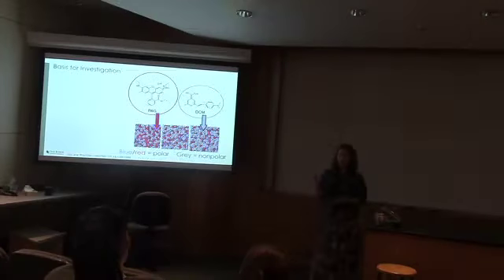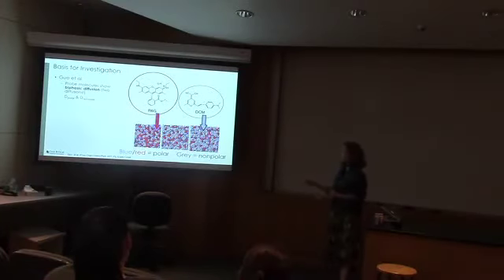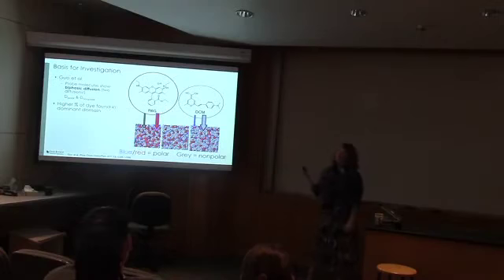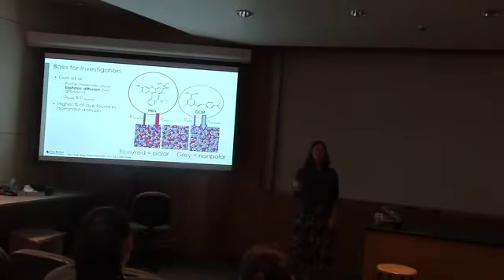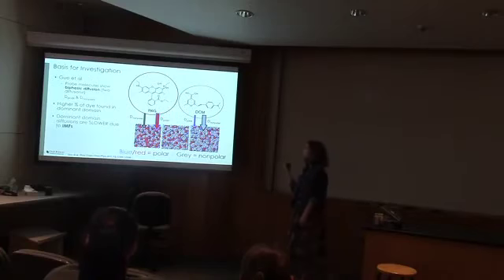So the basis for this investigation was that the Guo group showed that these probe molecules show biphasic diffusion, or two diffusions, which adds more to the story. Because we know that R6G has its dominant domain in the polar, and DCM has its dominant domain in the nonpolar. Well, it turns out a very small percentage of the dyes wind up in the other one when we put them into the liquids. So to reinforce, a much higher percentage of the dye is found in its dominant domain, but we still see a diffusion of a small percentage of the molecules in the other domain. And to add to the story, the dominant domain diffusions are slower, again, due to these intermolecular forces.